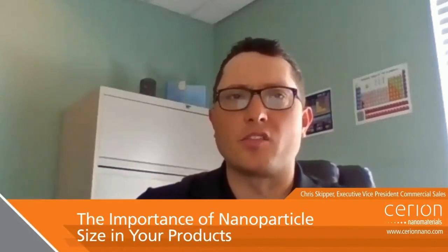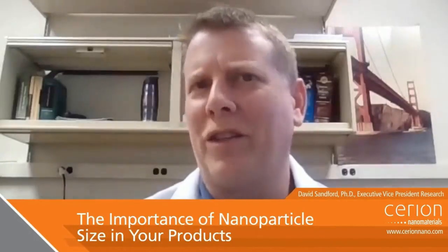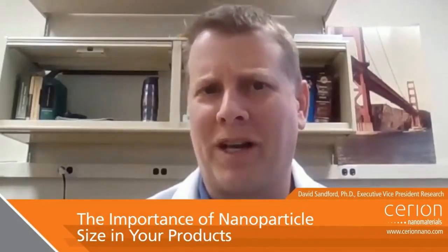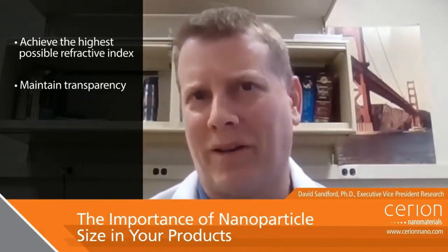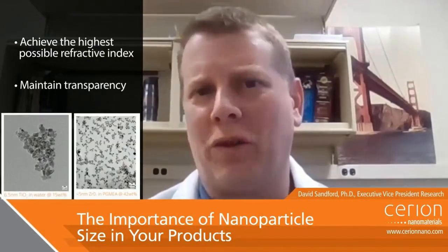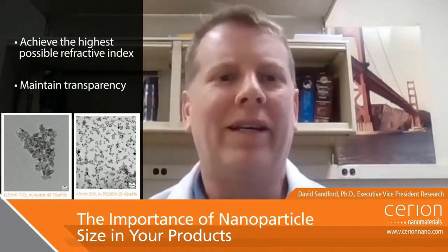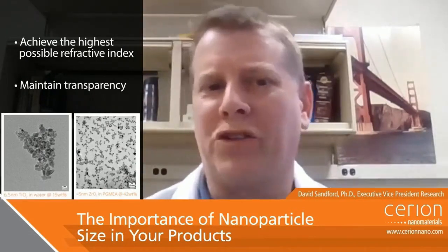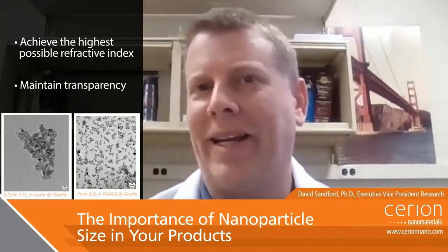Very interesting. What are the typical particle sizes of these types of nanomaterials? Well, most of the nanoparticles we make at Cerion are less than 30 nanometers in primary particle size. The particle size of titanium dioxide and zirconia is critical in achieving the highest refractive index boost possible while maintaining good transparency. If the particle size is too large, transparency could be negatively impacted. If the particle size is too small, it may limit the increase in refractive index. Since everything we do is tailor-made for our customers, we also try to understand their desired performance specifications and optimize our titania and zirconia accordingly.